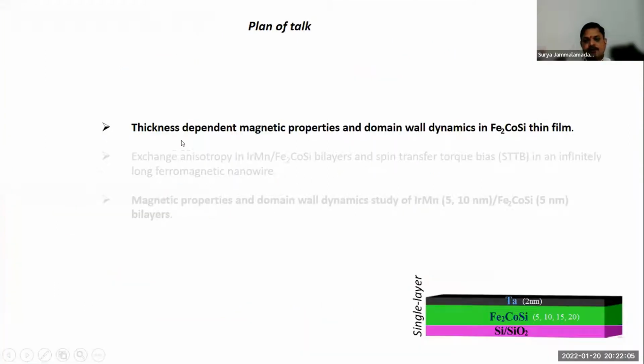So the first part of my discussion is about the thickness dependent magnetic properties and domain wall dynamics in Fe2CoSi thin films. In order to understand the domain wall dynamics and the magnetic properties of these films, initially we deposited Fe2CoSi films on top of silicon dioxide. To avoid oxidation, we deposited tantalum on top of the Fe2CoSi. The thickness of Fe2CoSi was varied as 5, 10, 15, and 20 nanometers.